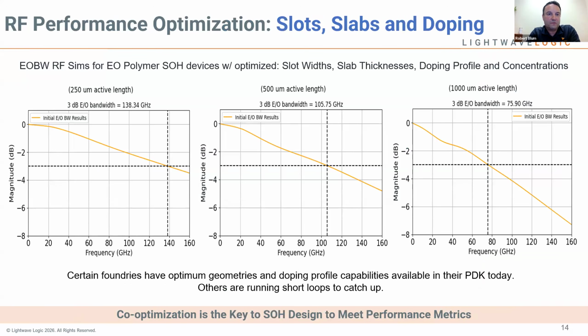And so, to give you some examples of the expected bandwidth, for example, here for different lengths. So, for example, if we make quite a short modulator, 250 micron long on the left-hand side, you see here we have a 3 dB electro-optic bandwidth of about 138 gigahertz in this simulation. And as you go to longer modulators, for example, the one on the very right would be 1 millimeter in length, so 1,000 micron length. Those show a 3 dB bandwidth of about 76 gigahertz.